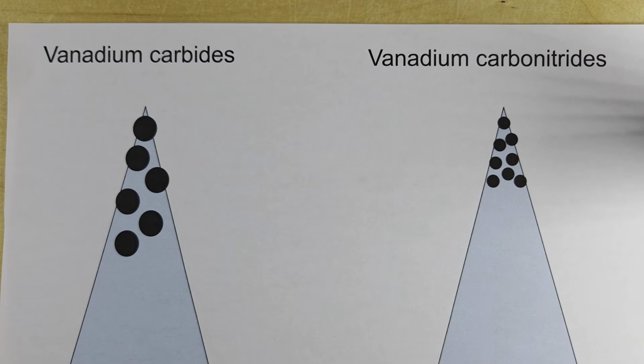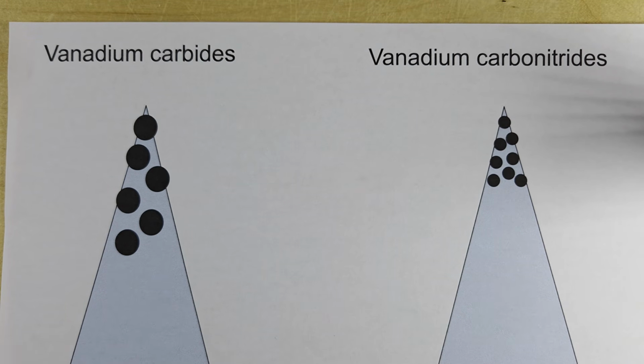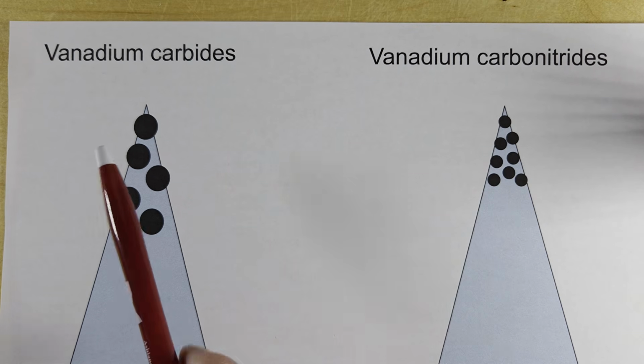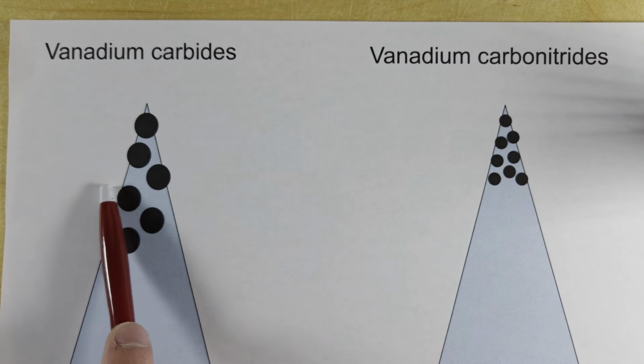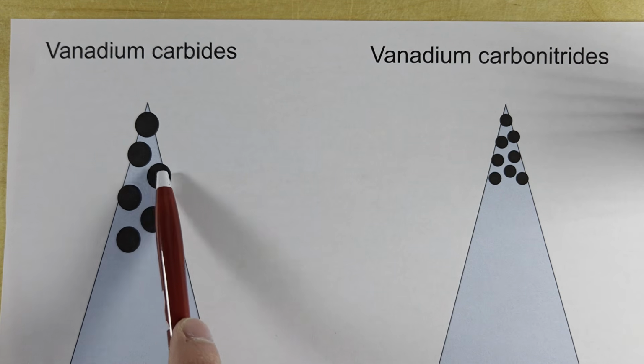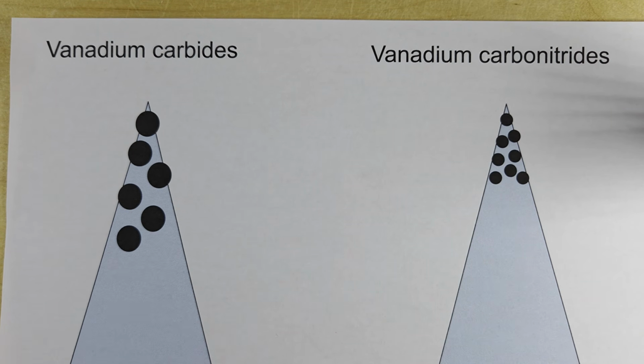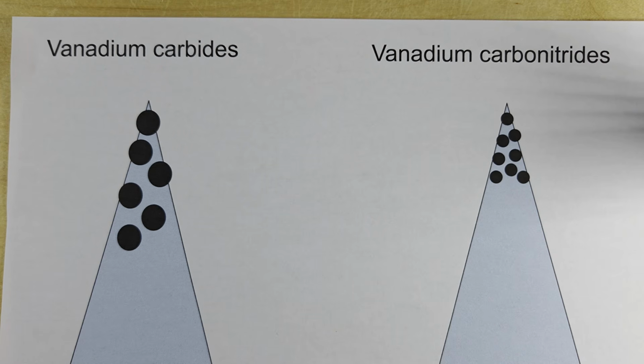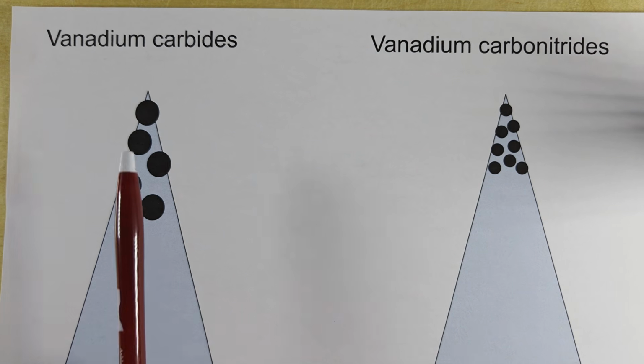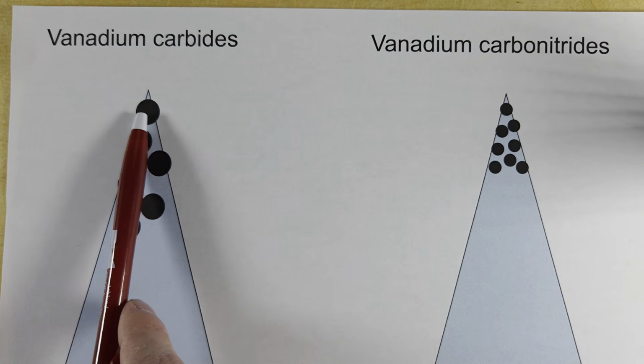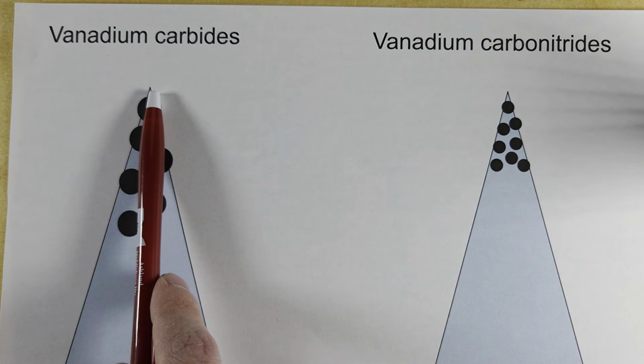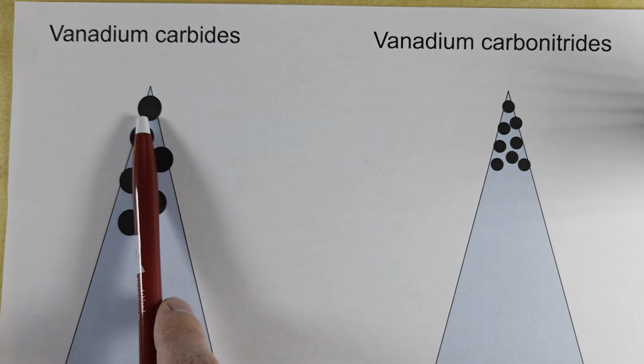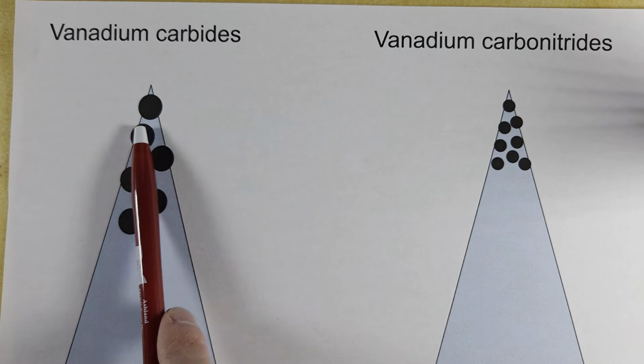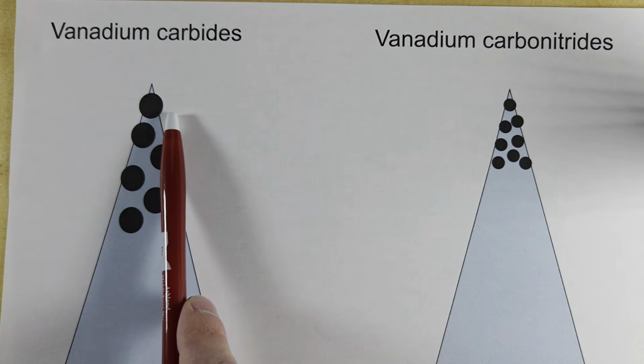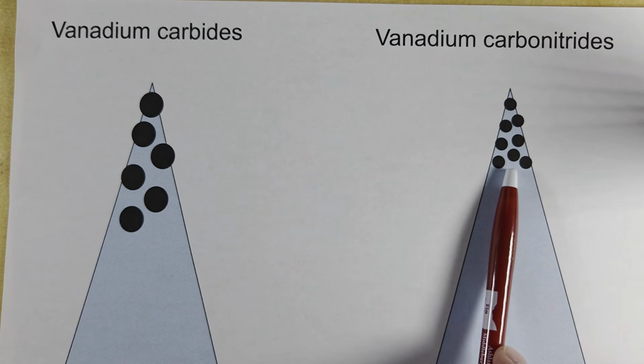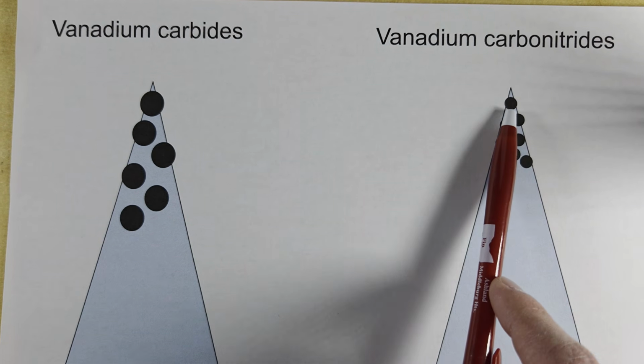So I made this diagram to help explain my theory a little bit with the carbonitrides. You can see on the left here I've got these vanadium carbides that are quite a bit larger than this side. Obviously these black pieces are the carbides, and they run throughout the entire edge. This is just a diagram of the edge that I made. As this apex wears down and the matrix wears out, you have so much carbide sticking out beyond the edge of the apex that there's less matrix holding this in place, so it's more easily removed from the matrix through cutting.